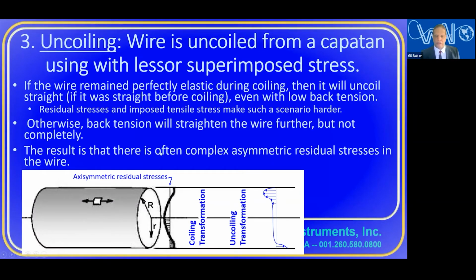So the ultimate result is there's often a complex asymmetric, now this is not axisymmetric, asymmetric residual stresses in the wire. We mentioned that this is the axisymmetric coming out of die 1. We're assuming it was axisymmetric. But then you had the coiling transformation, that's asymmetric, and you have the uncoiling transformation, also asymmetric. And so you might end up with a shape like this. Again, I just made this up, but I know that there will be compression in the wire here, and I know that there might be a little bit of tension here from the uncoiling.